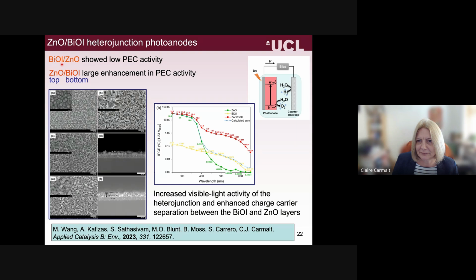And we think it's largely due to the formation of bismuth hydroxides, which are insulating, so it's not very active. However, if we have zinc oxide on the bottom and the oxyiodide on the top, it's much more efficient. So what we're interested in these as is the photoanode for use in photoelectrochemical devices.